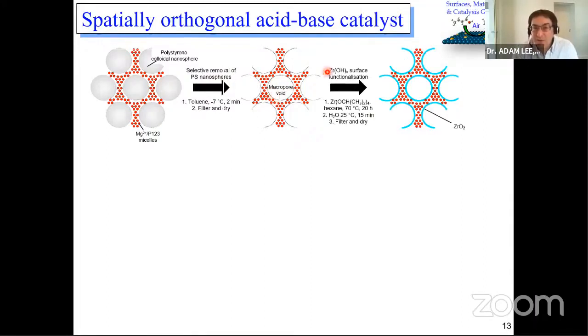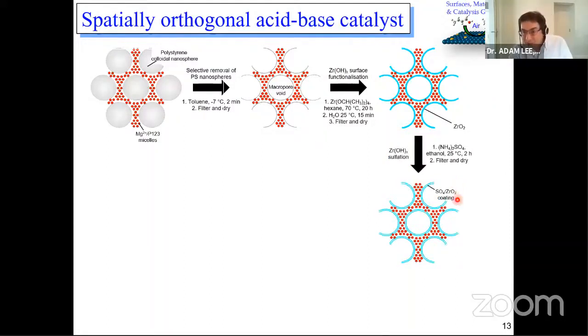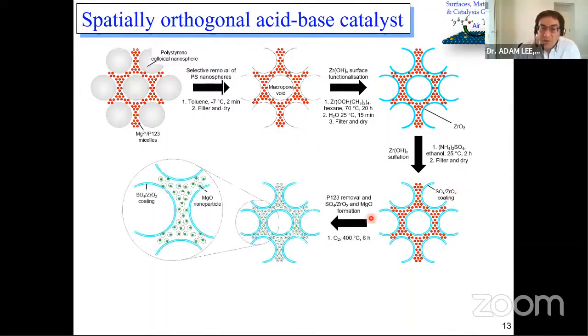In this case, we've chosen to functionalize it with a zirconium precursor to make a coating of zirconium hydroxide on the surface of the macropores. So the macropores have a zirconia coating, the mesopores have magnesium inside, and when we actually calcine, we can sulfate and calcine the material. I'll take you to the end step here. What you end up with is macropores that have sulfated zirconia, which is a superacid, a superacidic material, only coating the macropores. On the inside, in the smaller pores, we now have MgO nanoparticles. And magnesium oxide is a very good solid base. So magnesium oxide behaves a lot like sodium hydroxide, that's a liquid base, and sulfated zirconia behaves a lot like sulfuric acid. So here we've got solid acid and base forms of our traditional mineral acid and bases.